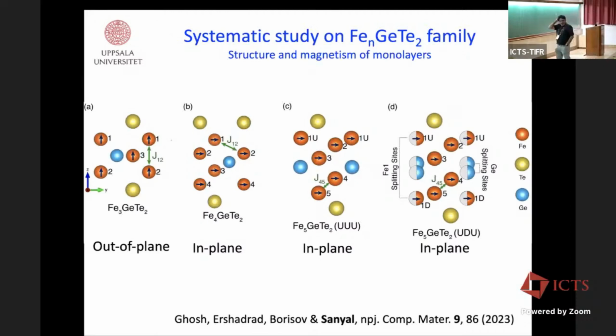Then we thought that, okay, that was a pure DFT study, the first study, because it's very difficult to do dynamical mean field theory calculations for this system. Nevertheless, we tried to do that for Fe3, Fe4, and Fe5 systems. And for all these systems, we did a systematic study of the electronic structure, exchange interactions, and corresponding TCs and things like that.